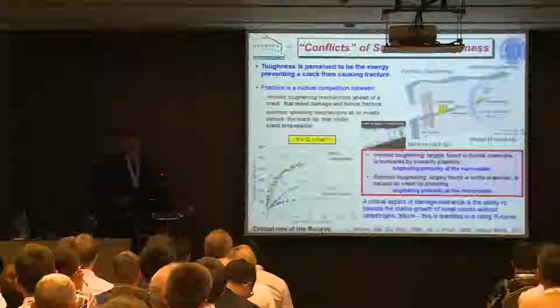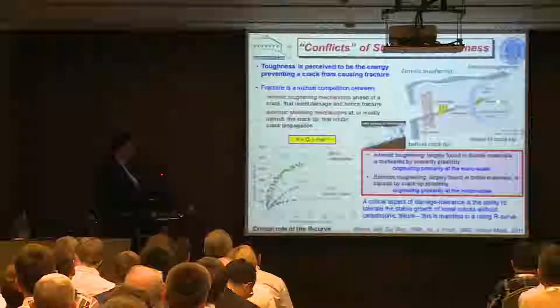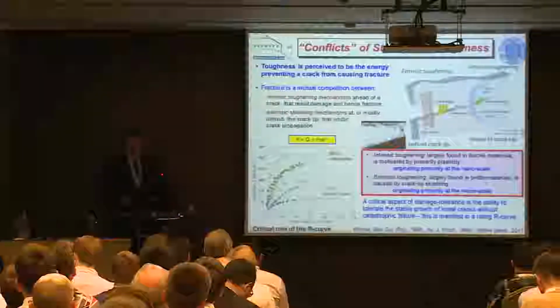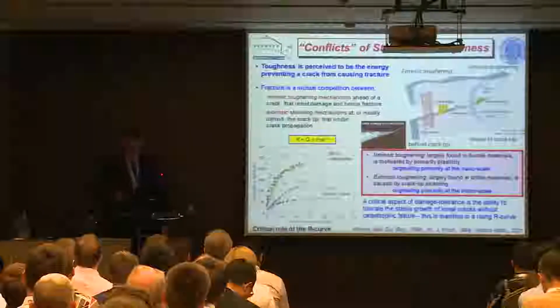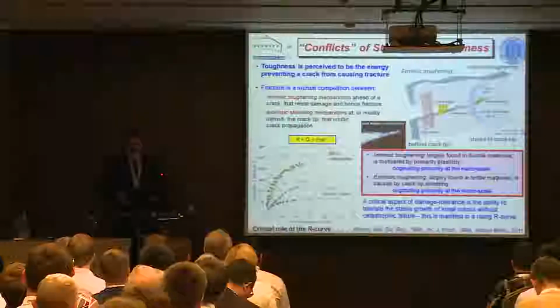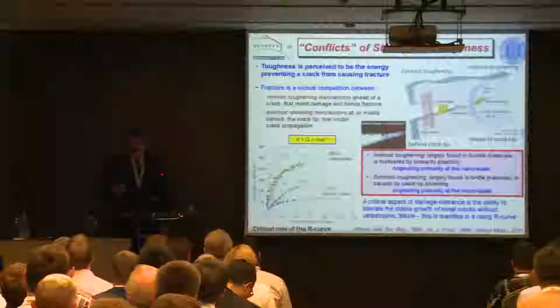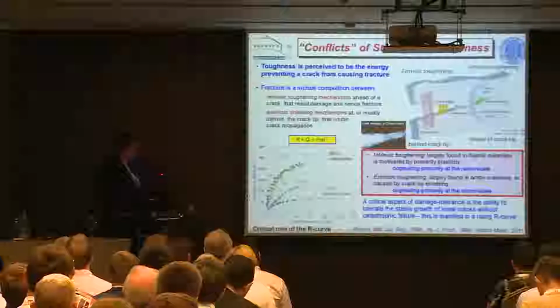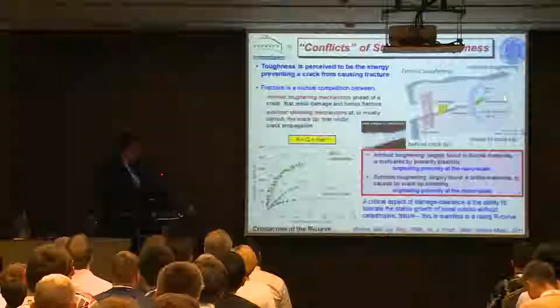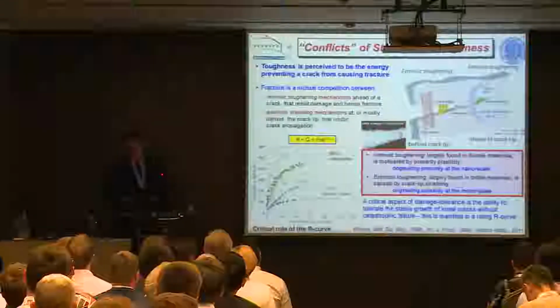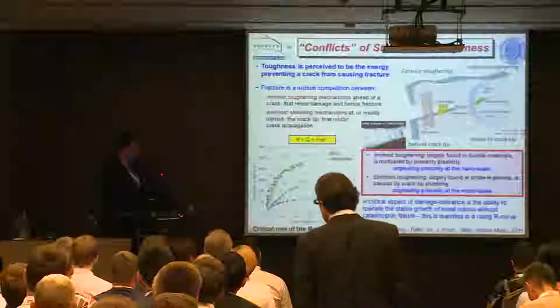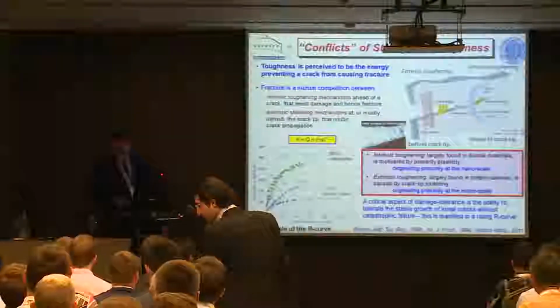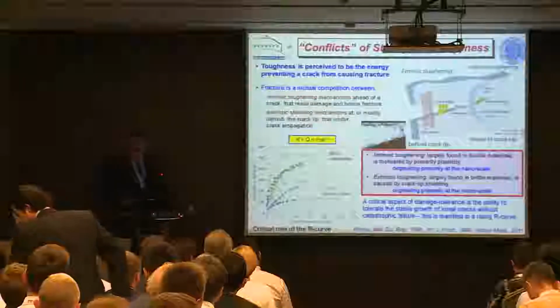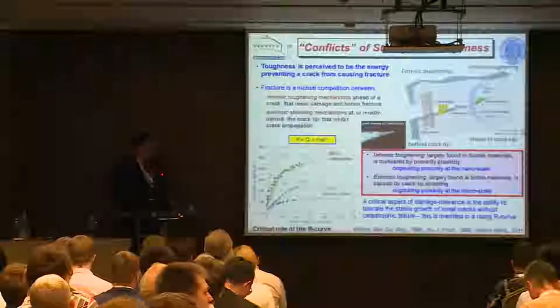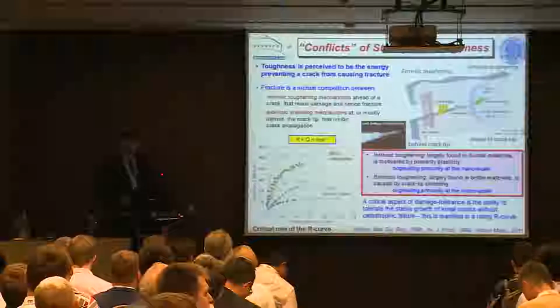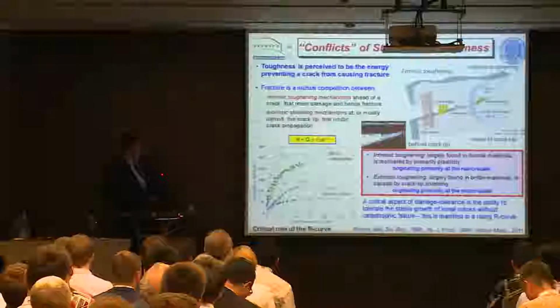but I think of fracture as a mutual competition between classes of mechanisms. They're what I call intrinsic mechanisms ahead of the crack tip, toughening mechanisms, and these are mechanisms that basically inhibit damage, whatever that may be, void growth, particle fracture, and so forth. And the prime factor here is basically plasticity. There are other things, but that's the prime thing. And these mechanisms take place ahead of the crack tip, and they really are how metals or ductile materials are toughened. But those mechanisms simply don't work when you get into a brittle material like a ceramic.